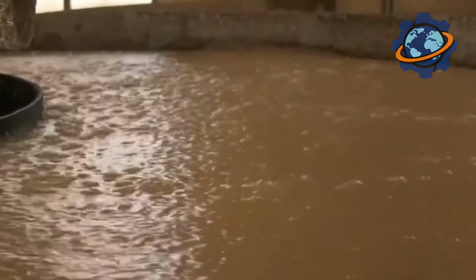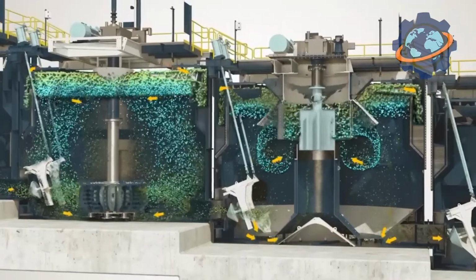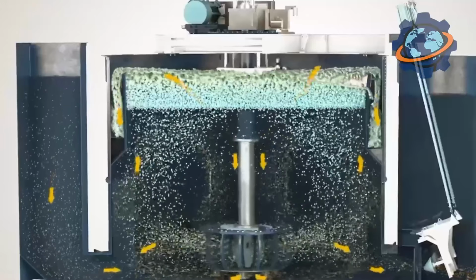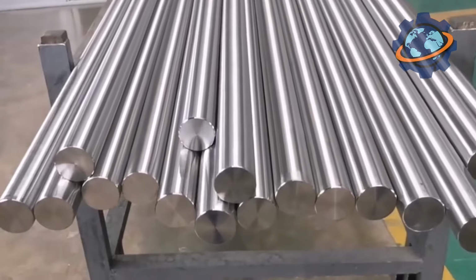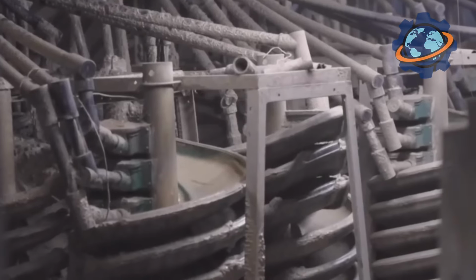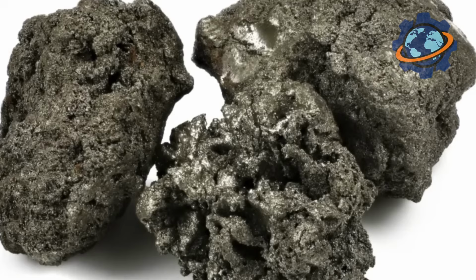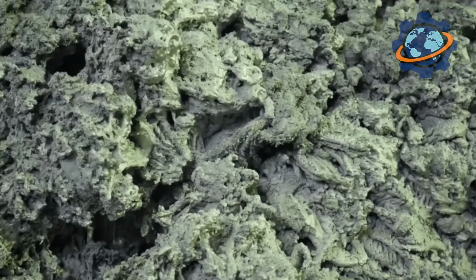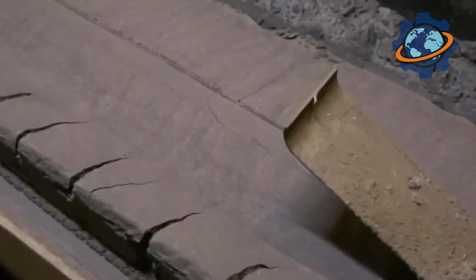First, it is enriched, separating the titanium minerals from the waste rock to obtain ilmenite or rutile concentrates. Then, the concentrates are subjected to chlorination, which results in the formation of titanium tetrachloride, a volatile substance that is purified by distillation. This process allows for the removal of impurities and the production of a high-purity intermediate product. Next, the titanium tetrachloride is reduced with magnesium or sodium in special reactors at high temperatures in an inert atmosphere, producing titanium sponge, a porous metallic powder. This titanium sponge is then pressed, melted, and cast to obtain ingots or billets for further processing.